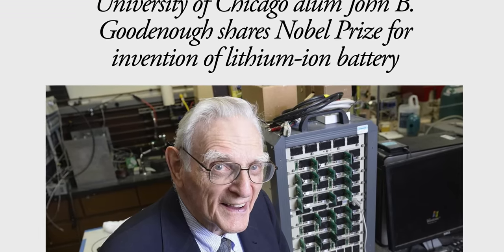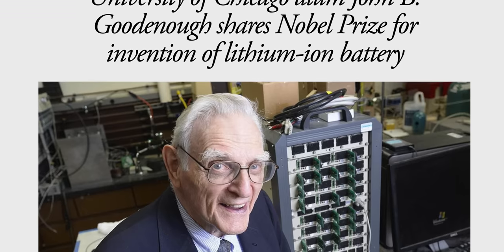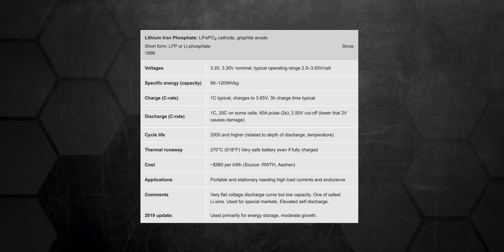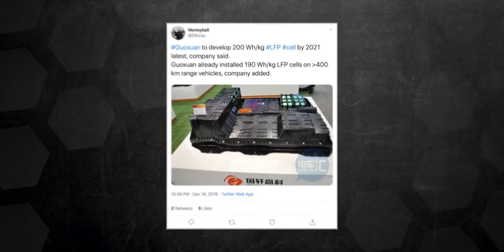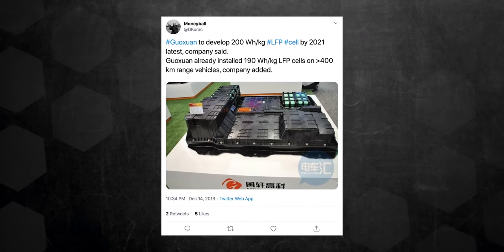In comparison, LFP batteries have no cobalt at all. Originally developed by John B. Goodenough's research team in 1996, LFP chemistry benefits from long cycle life, thermal stability, and excellent safety. Charging cycles are typically higher than NCA, and the high specific power and thermal stability means charging times similar to regular supercharging rates of around 150 kW or less. The downside is much lower specific energy than NCA — instead of 260 Wh/kg, you might be looking at 120. But CATL has shown their LFP batteries capable of 190 Wh/kg and may be closing in on 200.